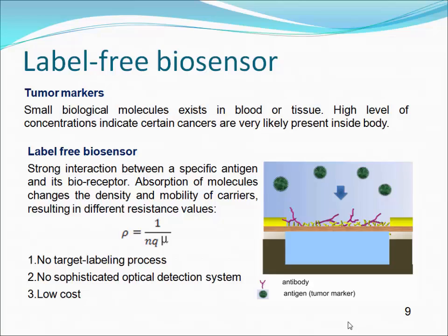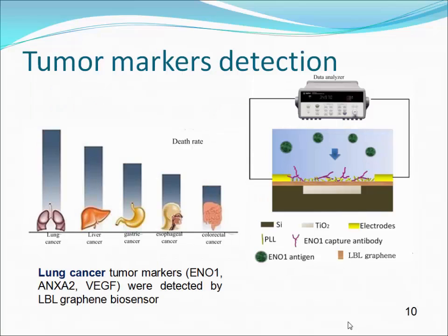We immobilized the antibodies on the surface of the layer-by-layer graphene film, and after it absorbs certain types of antigens or tumor markers, in our case, the carrier density and carrier mobility of this graphene will change. So it can result in different resistance values of the whole film. From the resistance value shift, we are able to know the concentration of the tumor markers. This kind of label-free biosensor doesn't need a time-consuming labeling process or sophisticated optical detection system, and it's very low cost. We use it to detect the lung cancer tumor markers.